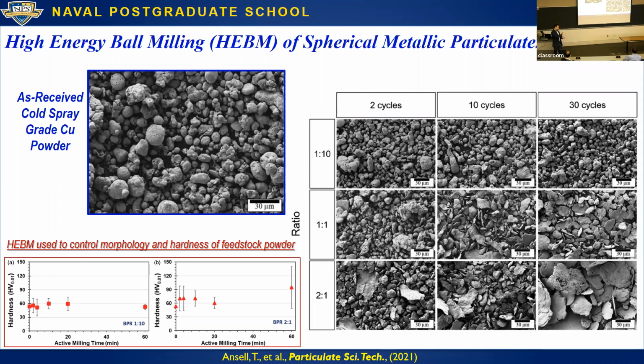The powder has to be able to spread very nicely on its own, since it's gravity fed. So you can imagine that if you're starting with something very fine, let's say just nanoparticles by themselves, that would be very sticky. You would never get a very nice flat bed. So using ball milling, we can control the morphology, and we can also control the hardness of those particles.